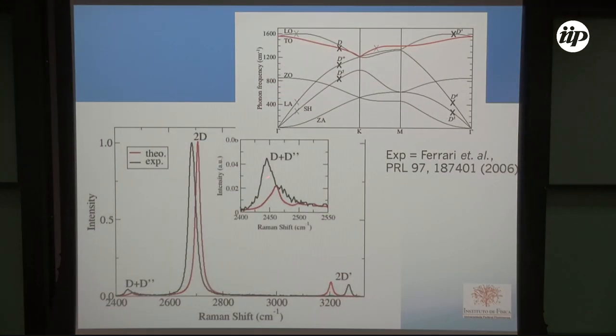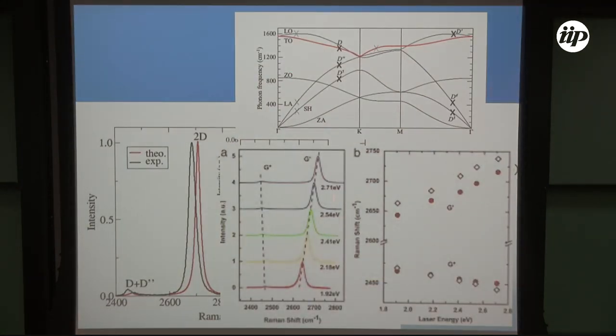Okay, so for instance, we can now look exactly where these peaks come from. The 2D peak, for instance, is two phonons from here, and the 2D prime peak is two phonons from here. So this is related to Alexandre's questions. Here, the electron-phonon coupling is much larger than here, and that's the reason why the 2D peak is much larger than the 2D prime peak. So now it's much easier for us to understand the data, because we can look at exactly the phonons that create these peaks, and we can learn a lot of physics with that. For instance, we can understand why this peak is dispersive, in the sense that when you change the laser energy, you change the position of the peak. I'm sorry, I didn't quote here, but this is the work by Daniela Mafra done in Marcos Pimenta's group. I keep forgetting to put the reference of this paper, but it's a paper by Mafra and Pimenta.